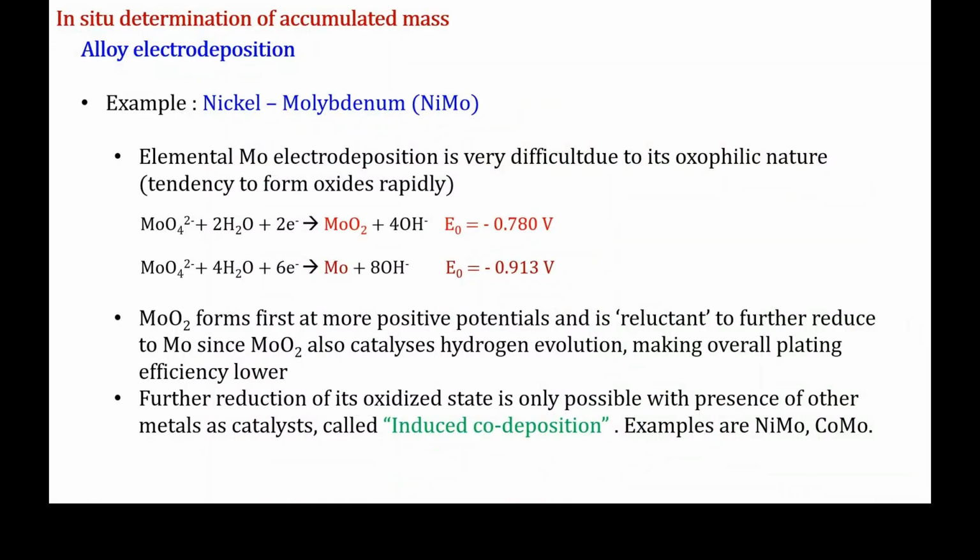Right, so the thing about molybdenum by itself is that it's quite a tricky metal. This has been known for quite a while now. And so elemental deposition of molybdenum is extremely difficult because of certain properties that it has. And the form in which molybdenum normally comes from a salt, it has an oxidation state of 6+, so unlike nickel, which requires 2 electrons for the reduction, this one requires 6. But what's normally observed is that at a smaller overpotential, you get a 2 electron transfer instead, and you get this molybdenum oxide forming. Now, oxides aren't amazing, as we sort of discussed.